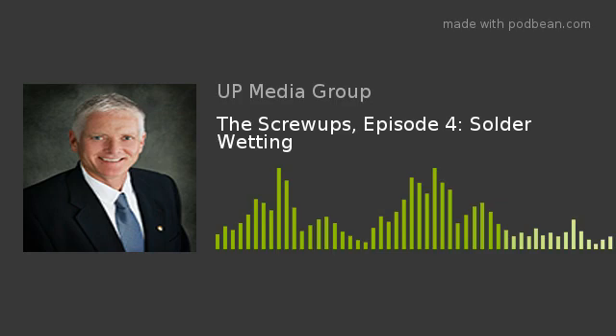So usually in my head, I don't necessarily articulate it, but I'm thinking, well, if the solder paste soldered every other component on the board perfectly, and one component is the difficult-to-solder component, it's fair to say the solder paste doesn't stink. It's fair to say that you've got a difficult-to-solder component for some reason. And that's where I say that the root cause can be divergent, because we don't exactly know why that particular component is difficult to solder or difficult to wet.